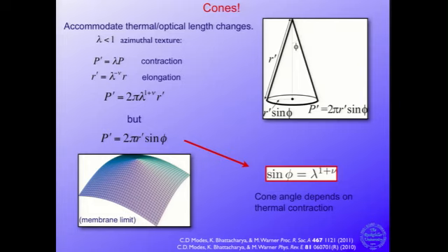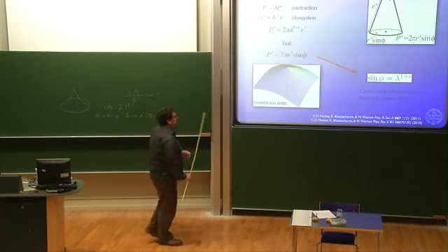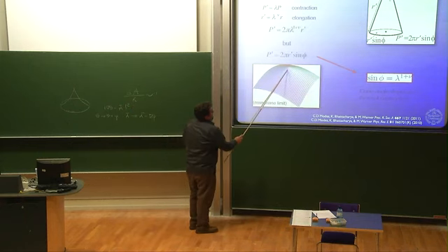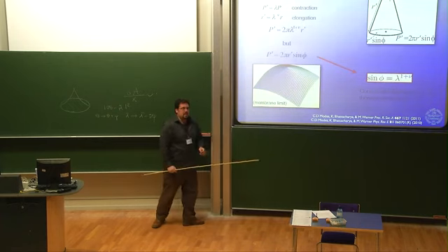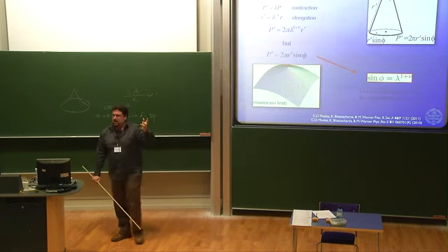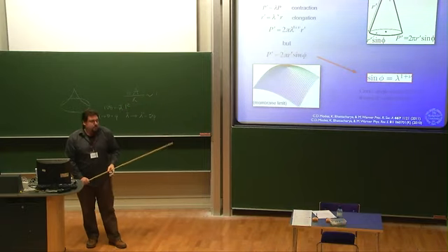Unless, and I will retract that assumption at various points throughout the talk, but I'll point that out when I'm doing it. One of those points is right now, which is, of course, at the very tip of a true cone, where the Gaussian curvature actually sits, the bending energy diverges. So if you had any real thickness at all, you can't have a true cone because of the energetics. And you can work out that Gaussian curvature becomes smeared out over the tip as a result of the bending energy, and you get a small spherical cap of order of the thickness of the material.